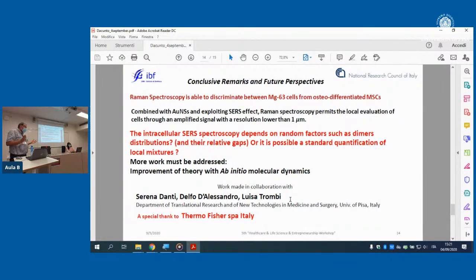This is a very simple method, the preparation of the sample is very easy. What you are observing depends on the dimers distribution, the number of dimers, and the relative gaps that you can control during the manufacturing of the sample. And by improving the numerical approach on what you are observing, you can discriminate the spectral mixture inside the gap.